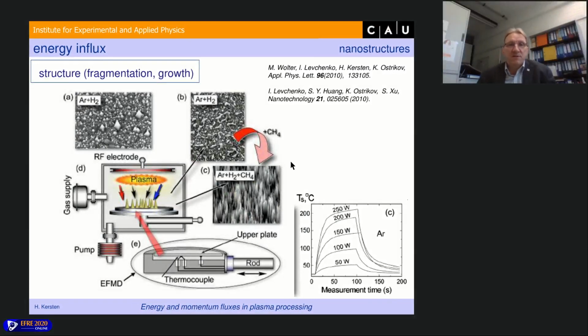And another example, we did some measurements with Australian colleagues together for growing small columnar carbon pillars, as you can see here. They are not carbon nanotubes, but small carbon pillars. And that was in methane and hydrogen plasma in argon. In order to grow these pillars, you need footprints, you need a catalyst, and they deposited a very thin nickel layer, a few nanometers, and then this nickel layer has to be structured, so that at these points, at the nickel dots, the carbonaceous columns can grow.